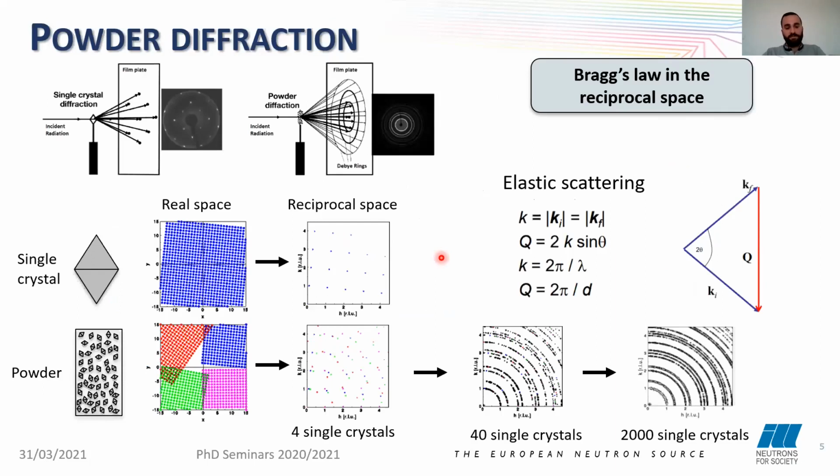So in powder diffraction, the basic constraint in order to see the Bragg peaks is the Bragg condition. We need to have the crystallite oriented at an angle where Bragg's law is satisfied for a given d-spacing. The diffraction pattern can be obtained in different ways depending on the nature of the sample. In order to obtain a diffraction pattern, or in other words, to see many Bragg peaks, we can do the following. When doing single crystal diffraction, it is necessary to scan the monocrystal through many different angles in order to record the whole diffraction pattern.